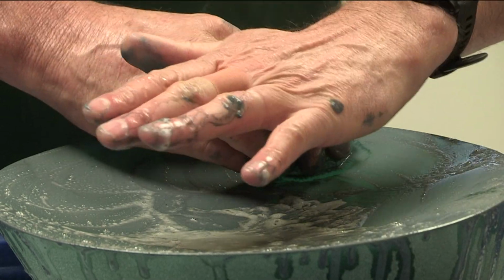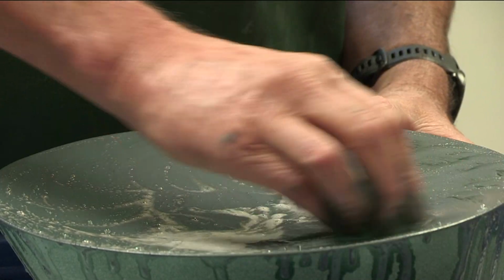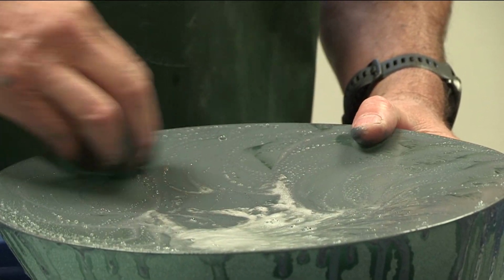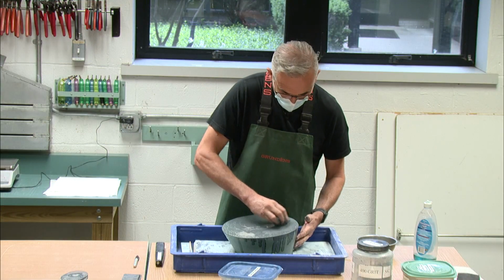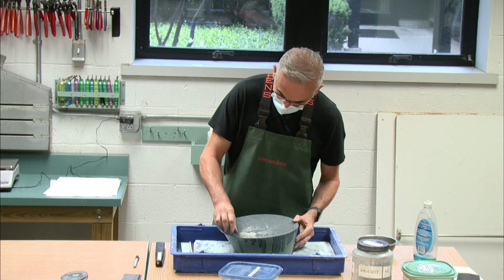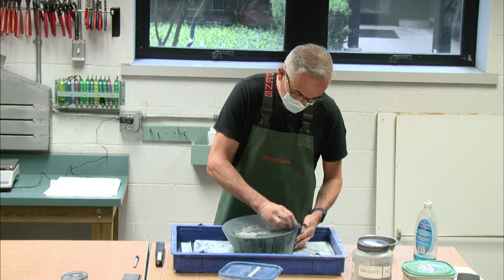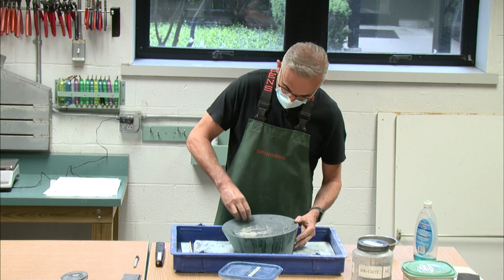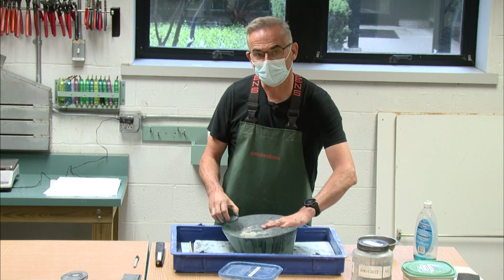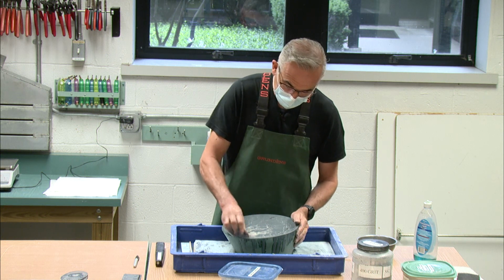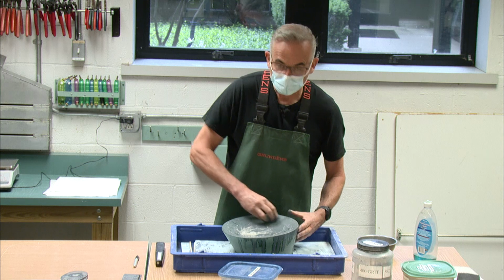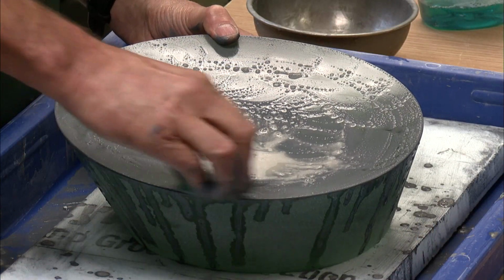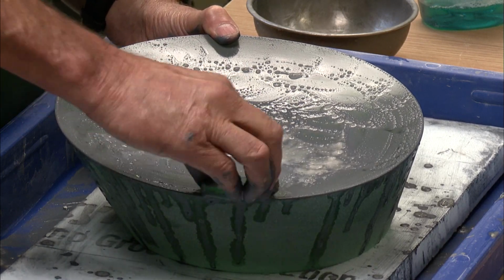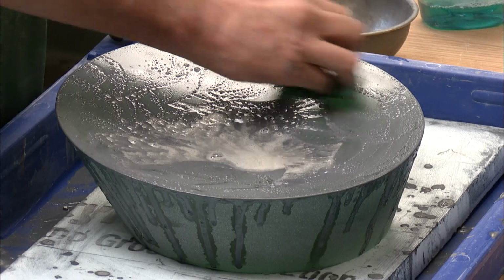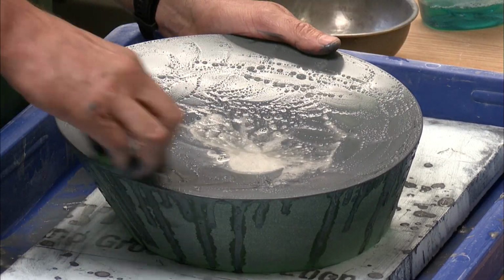So dishing that out, as I said, this was flat when I started. Dishing that out took about half an hour or so of heavy grinding, and little chips of glass were flying everywhere. So I was doing that in a cold working booth, so glass didn't spray all over the studio. And then I moved to that large piece of glass and I used an 80 grit just to establish that nice even curve. And from that 80 grit, once I was happy with that, I moved to 220 before using this 400 grit. So there's a series of steps that you go through. In all, it's probably taken about 3 hours of work to establish this surface.